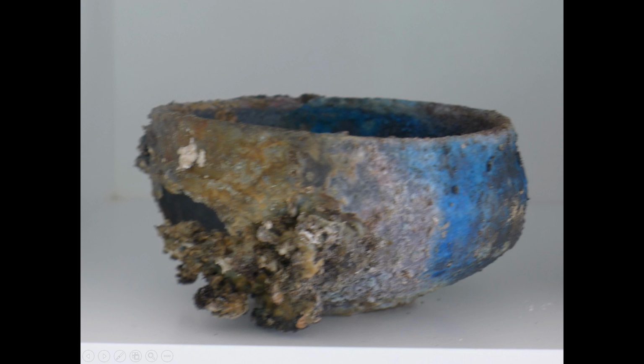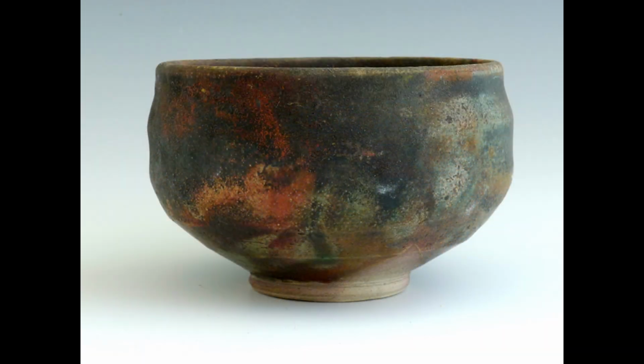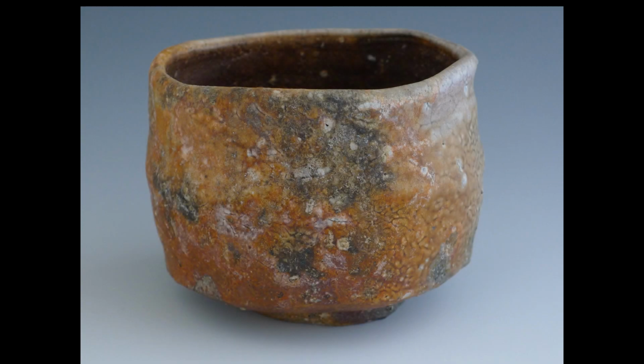But probably the takeaway here is you see that bright turquoise. That is sometimes what happens with the Oribe glaze. So that's what you're seeing there, just an incredibly bright turquoise color. Because of the heavy calcium in the wood ash, the calcium tends to make the copper in the Oribe glaze turn turquoise. And it'll do that within the kiln itself as well. You can get some turquoise and reds. Here's another glazed piece put underneath the firebox, and this was all green, and you can see again that micro reduction from the embers piling up, working very powerfully to make a variety of color.